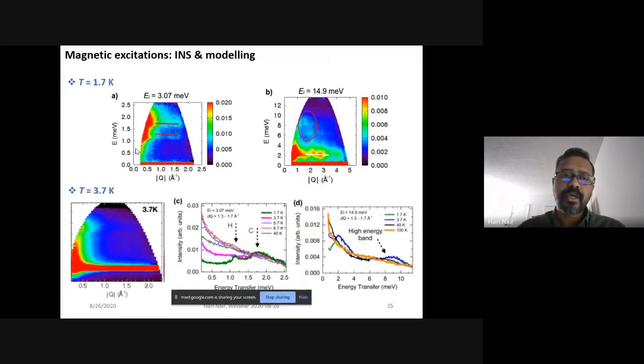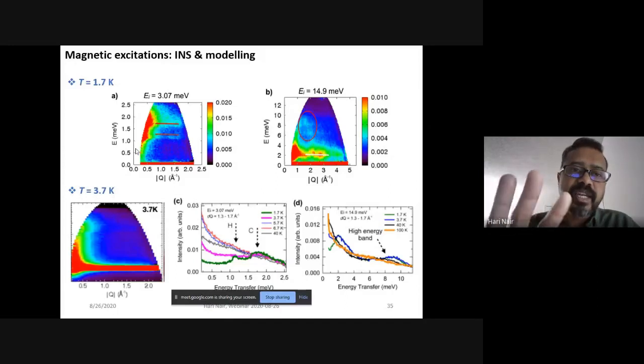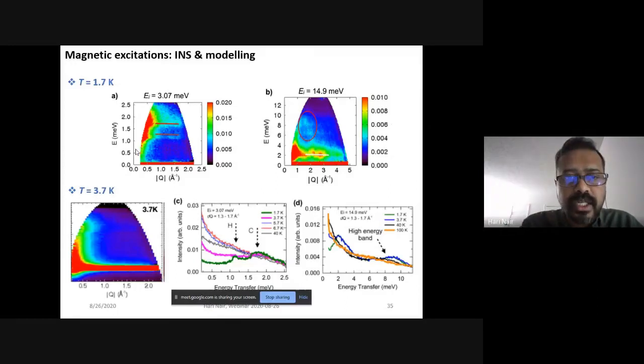Now we try to model them. So this section is a brief overview of what kind of modeling we did. The image A is a zoom of the 3.07 meV neutron incident case at 1.7 Kelvin. And if you zoom in, you can actually see two peaks, and I have indicated them with two horizontal red lines. So those are the two peaks probably emerging as excitations at low temperature, at very low energy.